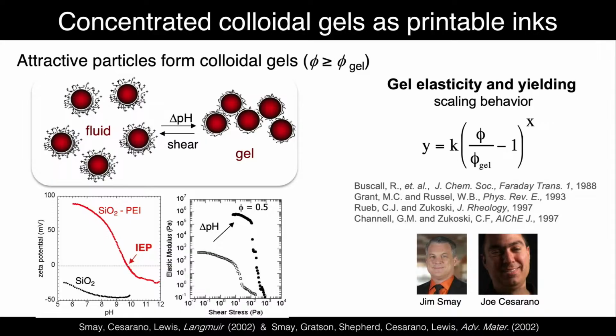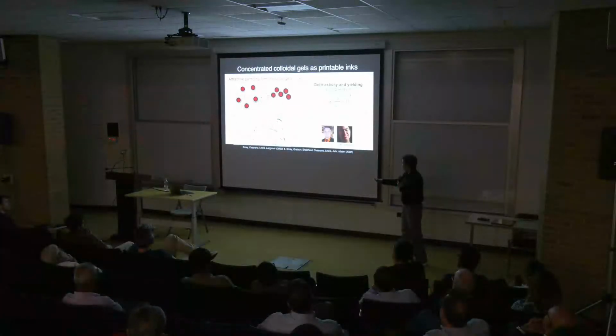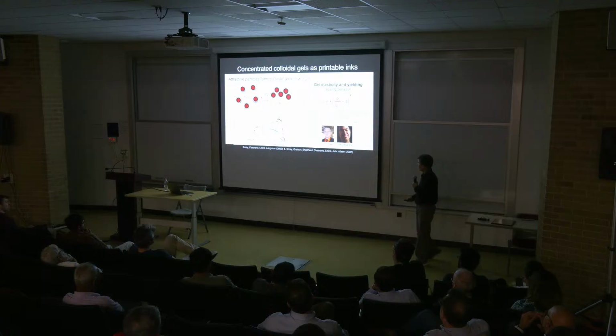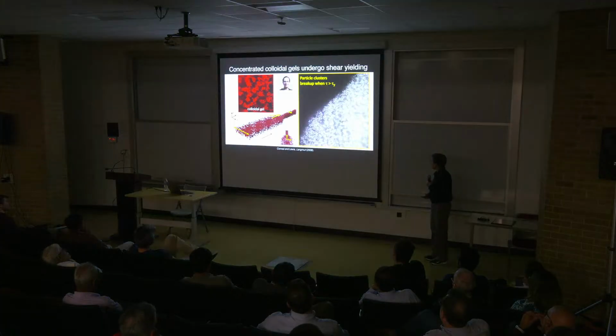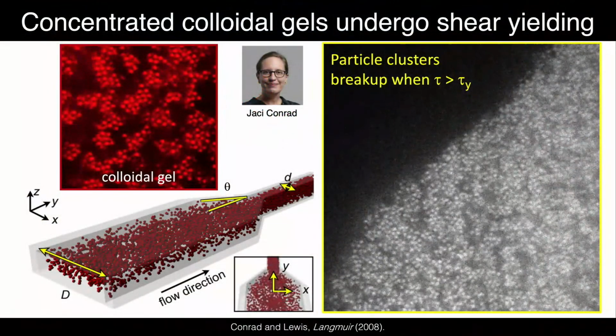But when we change the pH, we can go from a fluid to a gel. And that is what we use to tune the G prime, the shear elastic modulus, or the solid-like response of this material. And then working with Jaci, we tried to understand fundamentally what is happening in our printheads, as in these nozzles, as these particles are flowed through our nozzle.